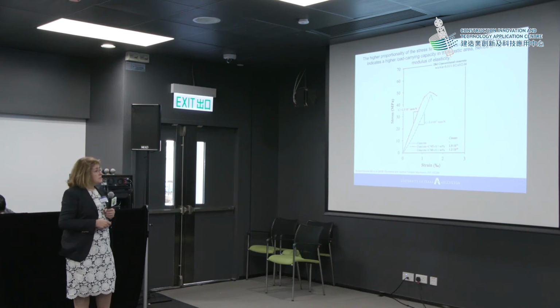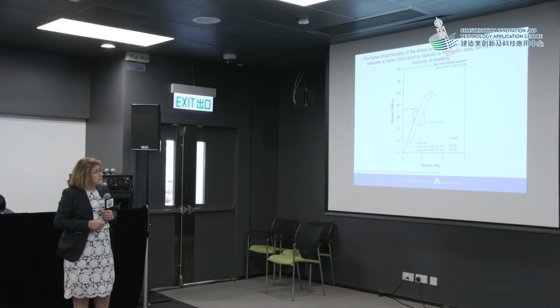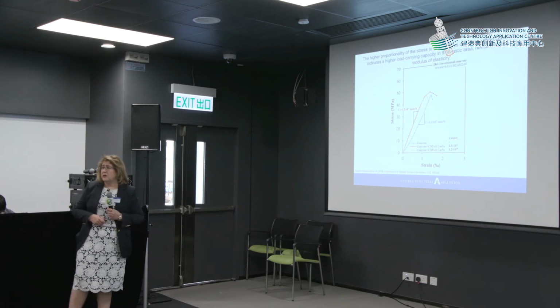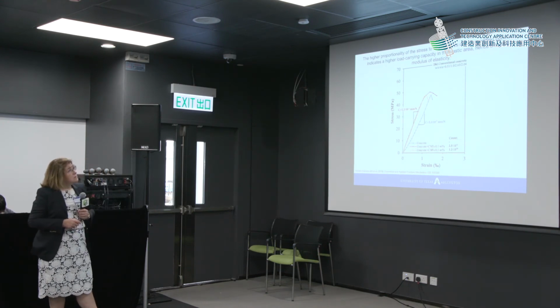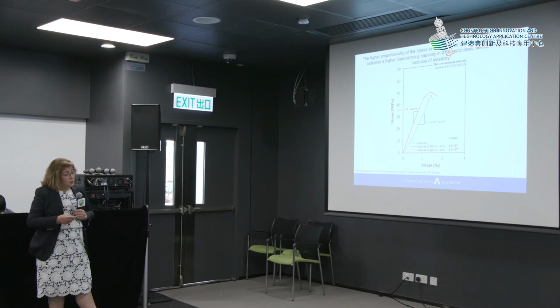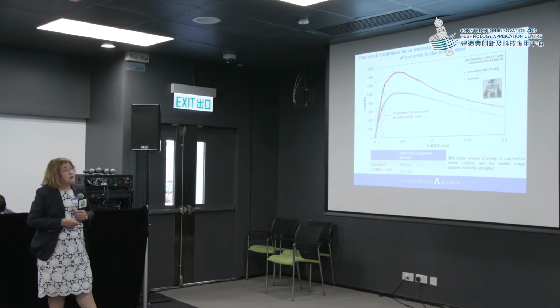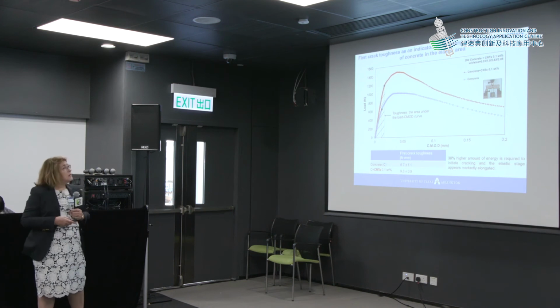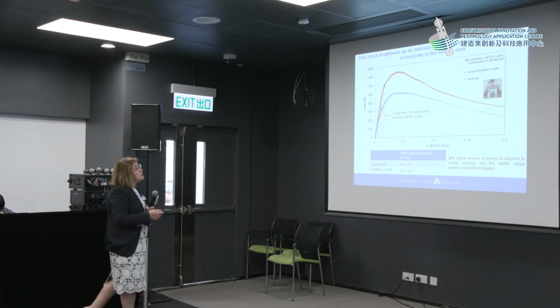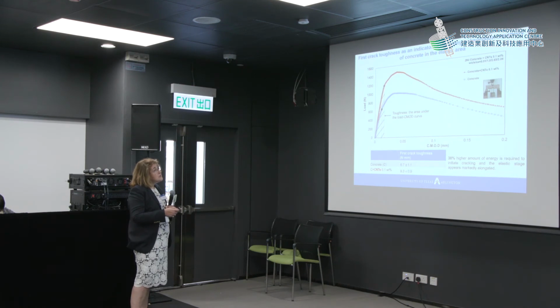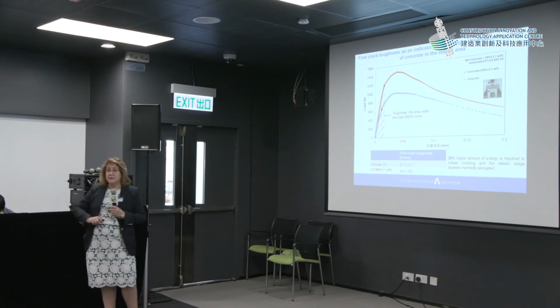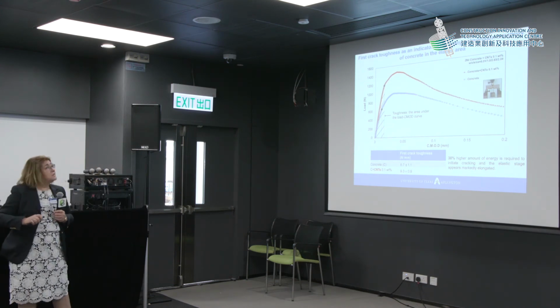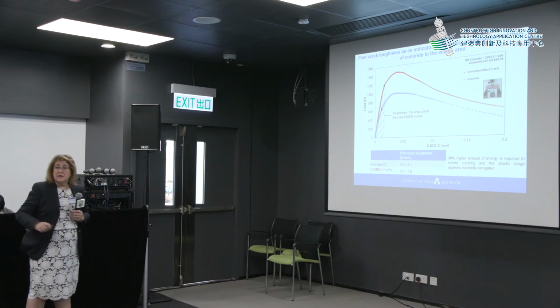We've done a series of experiments, and we've tested many types of concretes and mortars, plain, with carbon nanotubes, carbon nanofibers, and in different proportions of carbon nanotubes and nanofibers. And we were able to see that the higher proportionality of the stress-to-strain curves indicates a higher load carrying capacity in the elastic area. We were able to see the same effect in all our mixtures. And actually, we were able to identify the first crack strength here, which is the first point in a stress-strain curve where the curve deviates from the proportionality that we want to see in the elastic stage.